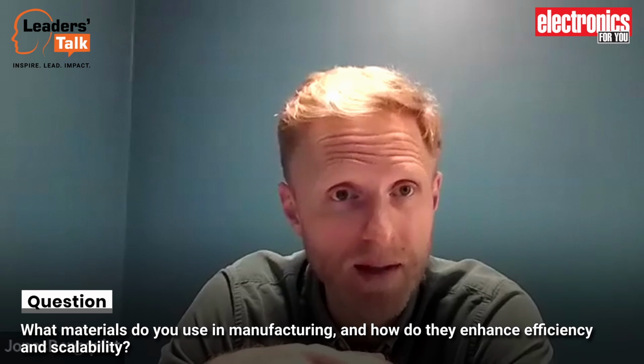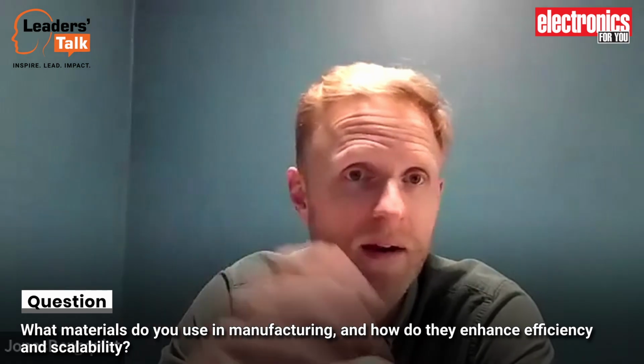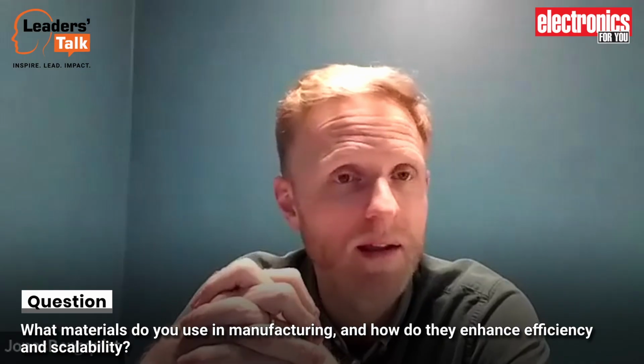The substrate we are using is PET, and I said the thickness of the solar cell is 200, I think it's actually maybe 210 micron. PET constitutes about 200 micron of this, and the solar cell is less than a micrometer in total. For the solar cell material, it's basically conjugated organic molecules, and the rest is PET, if you look at the main components. And then there is a small silver print on the side to conduct the current from the solar cell out to the contacts.